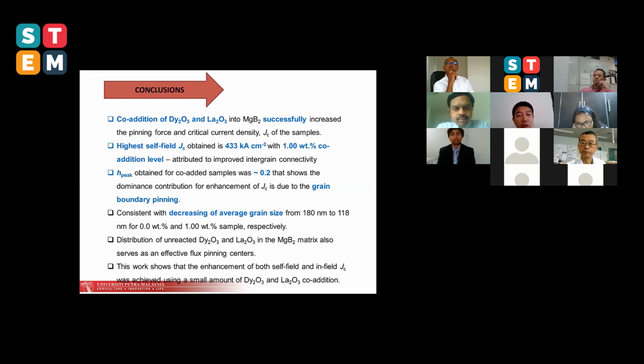The increase in self-field Jc is attributed to improved grain connectivity. However, when we plot the flux pinning versus reduced field, we notice that the field dependence of Jc increased. That is due to the grain boundary pinning. Again, this is consistent with the decrease of the average grain size of the samples with the co-addition level of those dopants. So we show that Jc can be increased greatly by using a very small amount of co-addition of dysprosium oxide and lanthanum oxide.